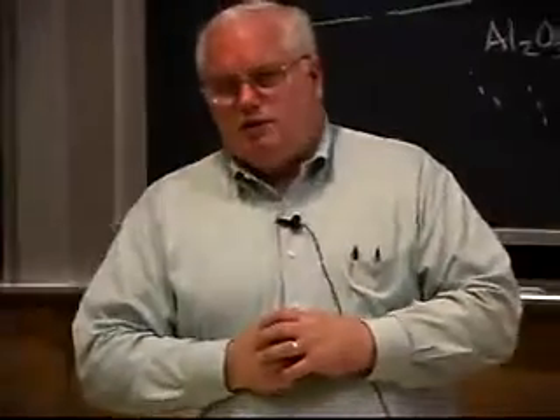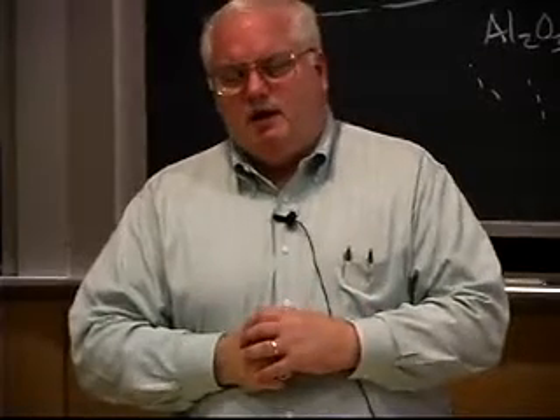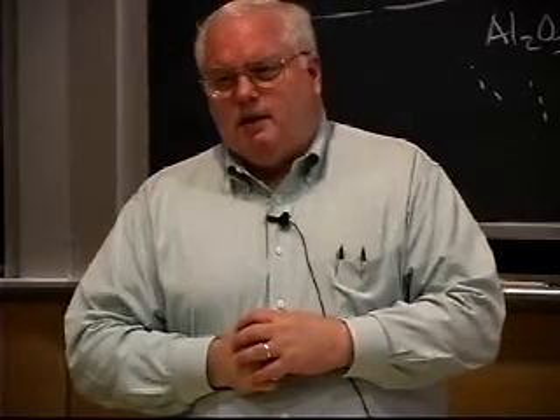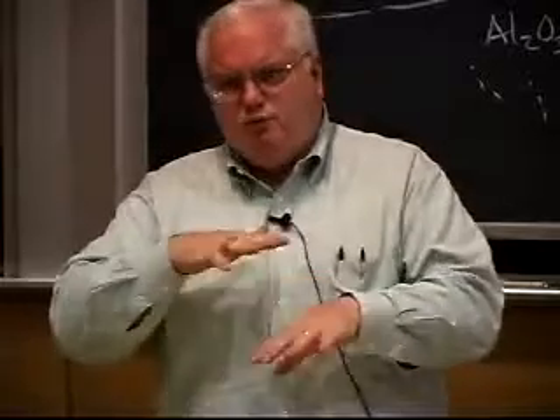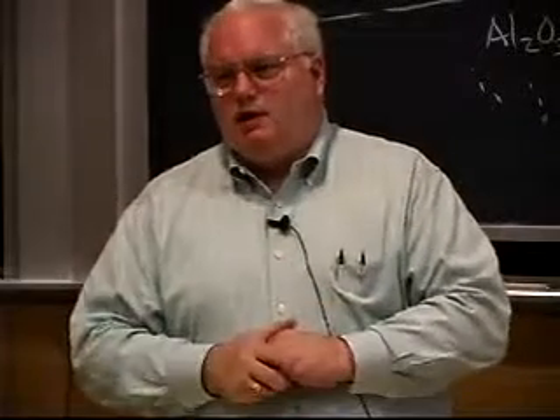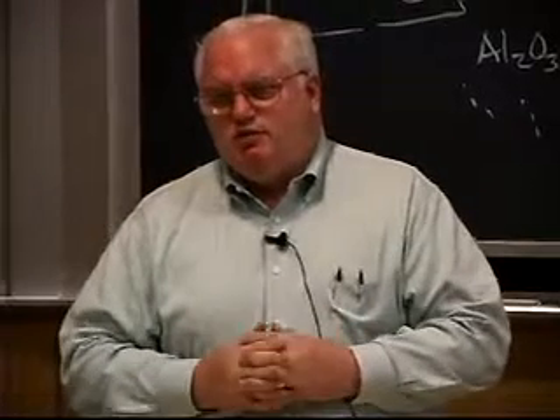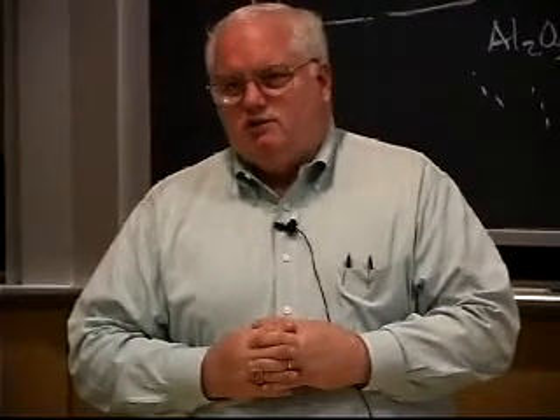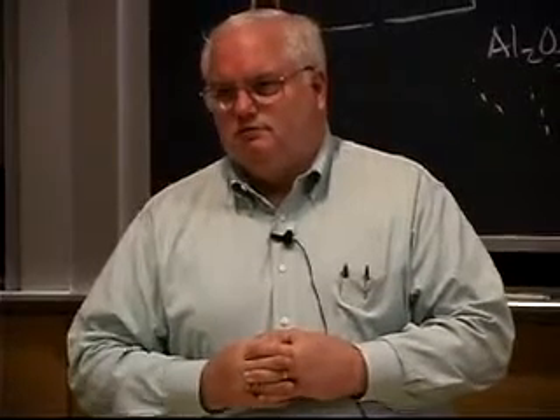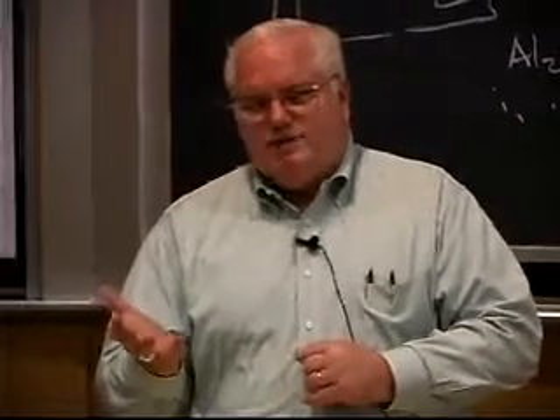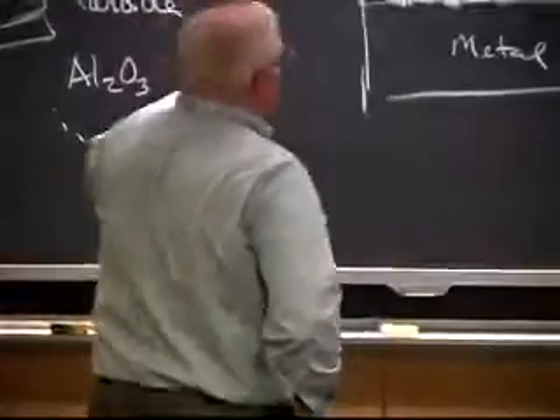And they were telling me how sometimes they have some problems. Might be a high humidity day or something, and they couldn't get good bonds. And these things were failing their tests and whatnot. And I thought, boy, well, we could put essentially a braze alloy and kind of braze the surface or something, or make a transient liquid phase diffusion bond. And then I realized, before I actually told them to do that, that would be the worst thing they could do. Okay?